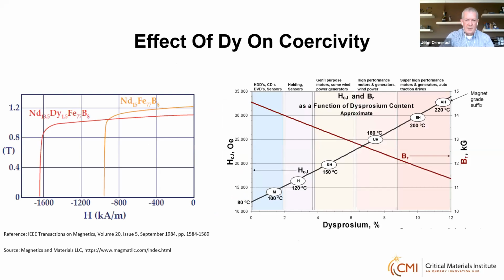And this chart on the left here is actually from a publication way back in 1984 by the Sumitomo Special Metals team. And what you can see is that the substitution of dysprosium into the ternary system dramatically increases the coercivity. Now, unfortunately, there's some loss in remanence because the heavy rare earths tend to couple antiferromagnetically with the iron lattice and reduce magnetization. But coercivities are dramatically improved. So it's become standard and common practice to add dysprosium or in some cases terbium to improve the coercivity and thermal performance of these magnets.